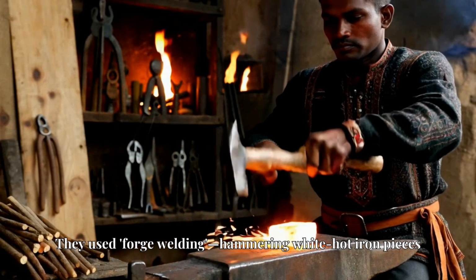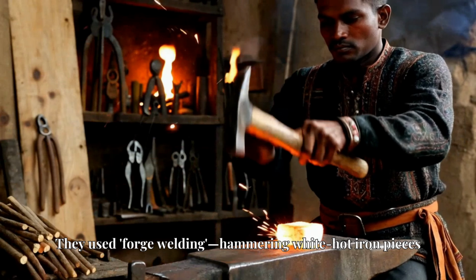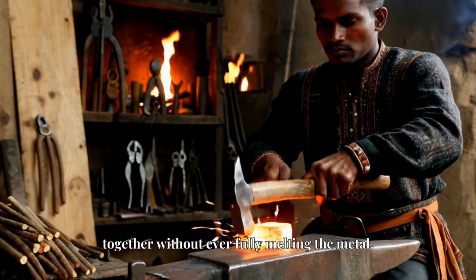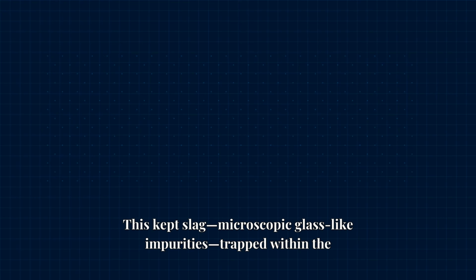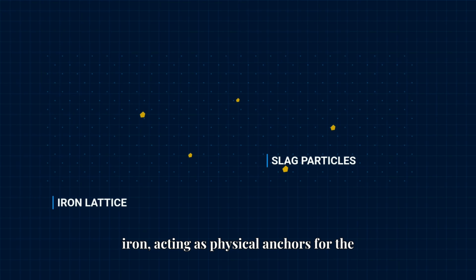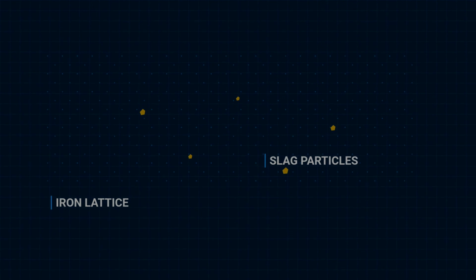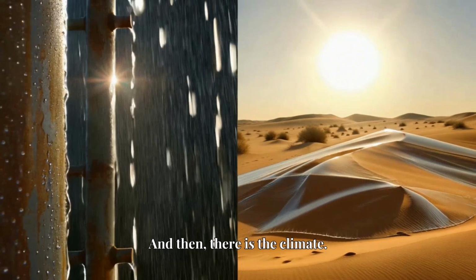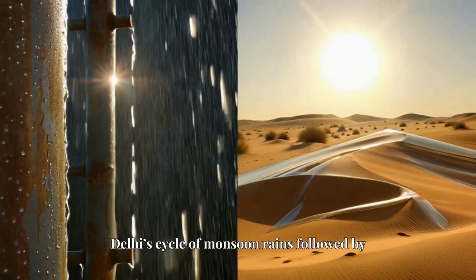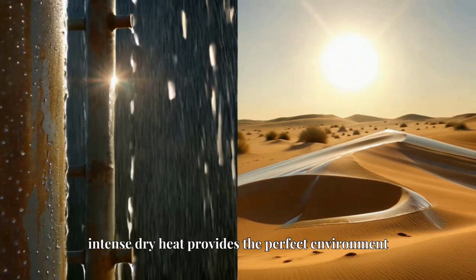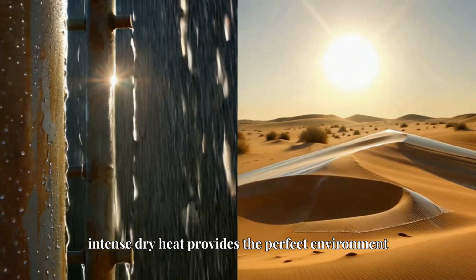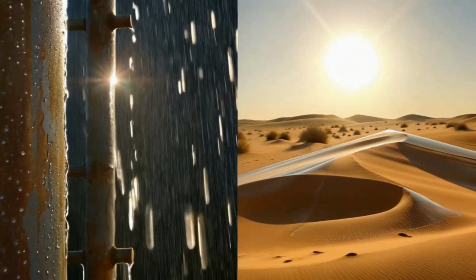They used forge welding, hammering white-hot iron pieces together without ever fully melting the metal. This kept slag, microscopic glass-like impurities, trapped within the iron, acting as physical anchors for the protective film to cling to. And then, there is the climate. Delhi's cycle of monsoon rains, followed by intense dry heat, provides the perfect environment for the film to stabilize.